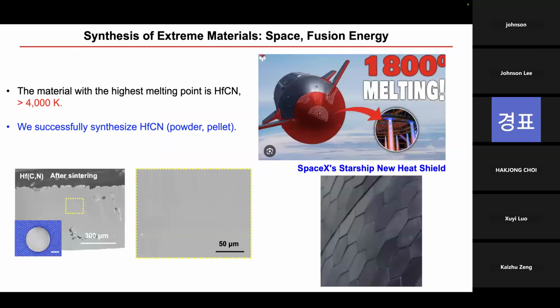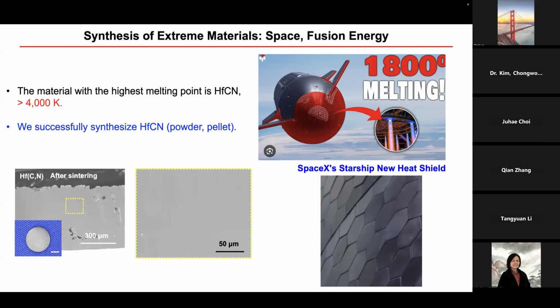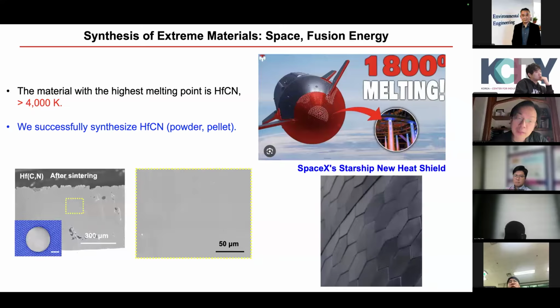And of course, high temperature materials, refractory metals. Here we demonstrate hafnium carbon nitride, the highest melting temperature material, with a melting temperature of more than 4,000 Kelvin. We successfully made a pellet out of hafnium carbide and hafnium nitride. You mix the powders together and sinter them, and in a few seconds you can get this hafnium carbon nitride. And why is it important? What's the big deal, right?